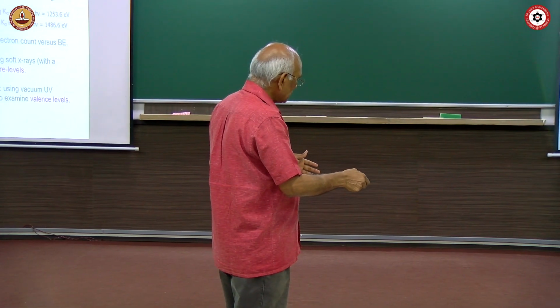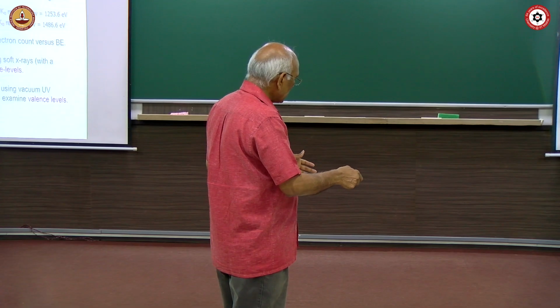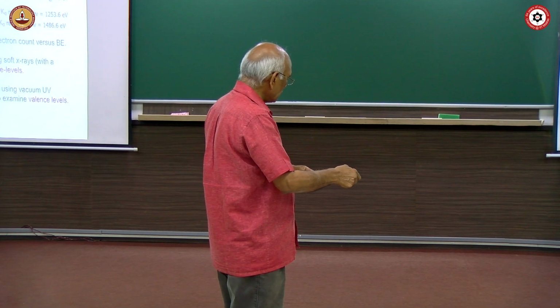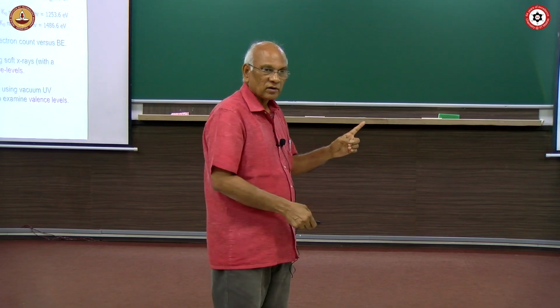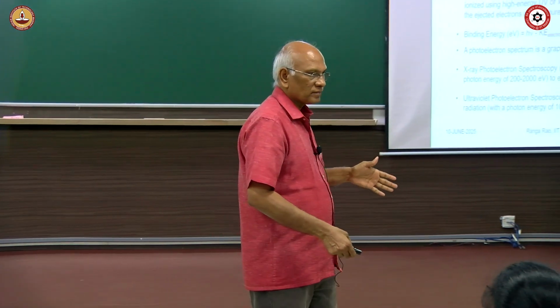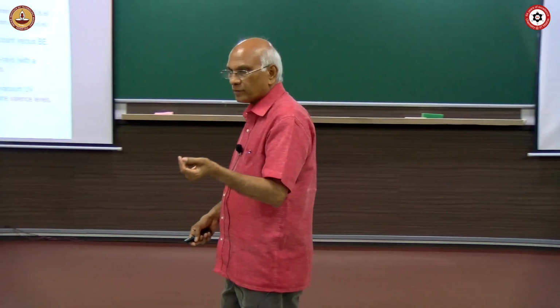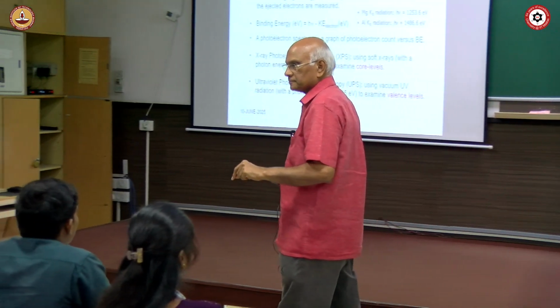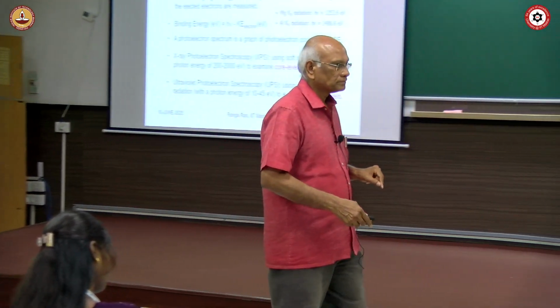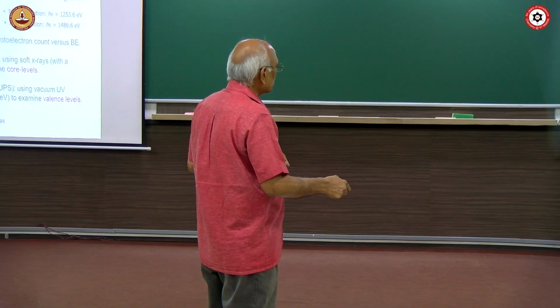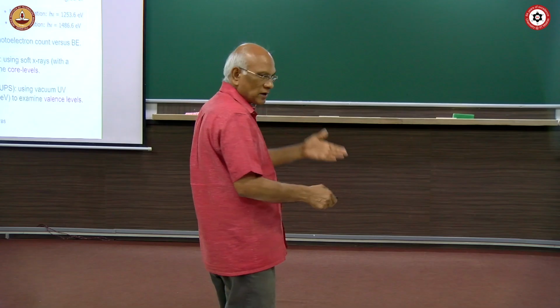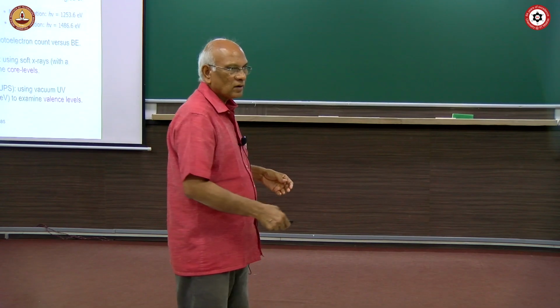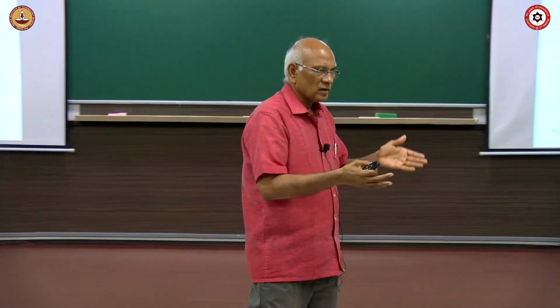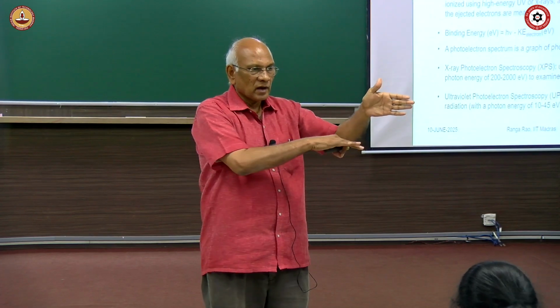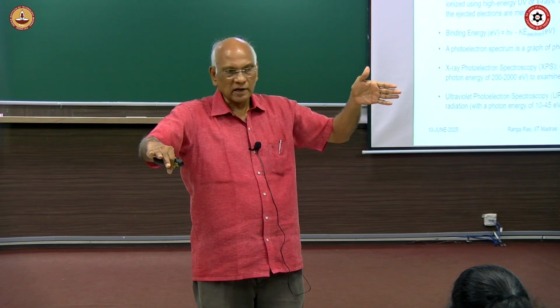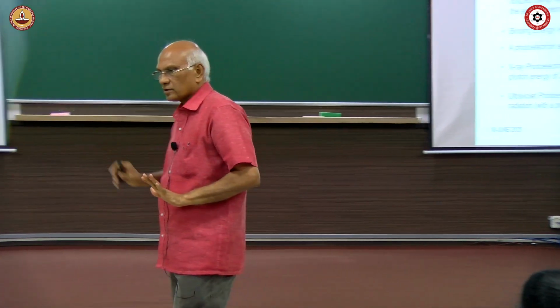Once you define this, like in this case for example these two, you can measure the kinetic energy of the electron that is coming out. You know the value of h nu, you subtract the kinetic energy, and you get the binding energy of the electron that is coming out from the sample, or from atoms present in the sample. That is the more precise way of saying that. Okay, all right. So, a photoelectron spectrum is nothing but the number of electrons coming out versus the binding energy or kinetic energy. It can be the number of photoelectrons coming out on the y axis and then kinetic energy or binding energy on the x axis. That is a photoelectron spectrum basically.